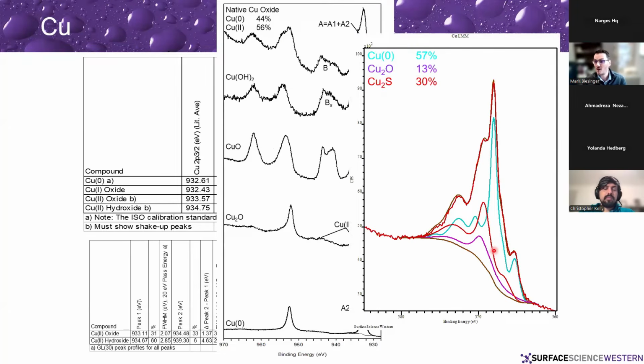And then we've done a lot of curve fitting, particularly of the Auger peak, which has been very effective at pulling out what species we have. For example, we've got so much copper metal, so much copper 1 oxide, and so much copper 1 sulfide. If you looked at the corresponding copper 2p spectrum, you'd have a single peak with no information coming out of that as to how much of these things you have. Whereas here we can pull out quantitatively or semi-quantitatively how much of the different species we have, those copper 1 species and copper 0 species.